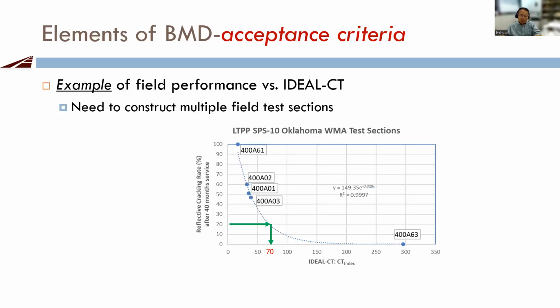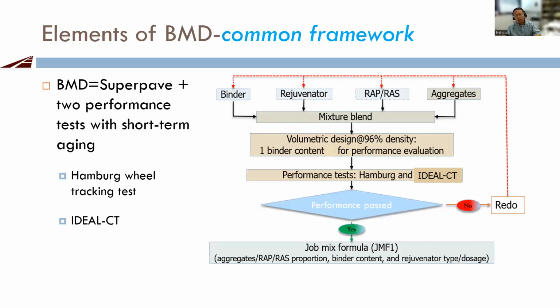Another example is field performance test sections. I'm using the SPS 10 in Oklahoma. That's a warm mix test section, and over there I have 5 test sections. This is the overlay ideal CT test results. This shows observed reflective cracking after 40 months of service. If you want to pick 20% reflective cracking, you get the criteria 70. That's ideal CT index 70. That's another way to establish it: with the field performance and your CT index number, draw a curve, then you pick your minimum tolerance, and you get your CT index criteria.